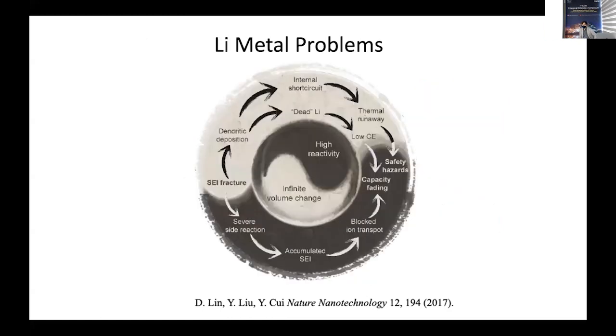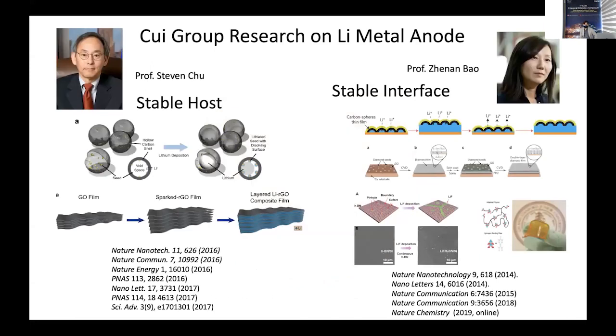So indeed, we share with the whole community the root causes of the problem. One is the infinite volume change in the relative sense. And the second is the really high chemical reactivity of lithium with the electrolyte, which causes all the surrounding problems we observe when we made the batteries and did the measurements. So in order to solve these root causes, we came up with a strategy, working in collaboration with Steve Chu and Zhenan Bao at Stanford. To the left, we propose for the first time a stable host for lithium metal. In the past, the lithium metal people used was just a foil.